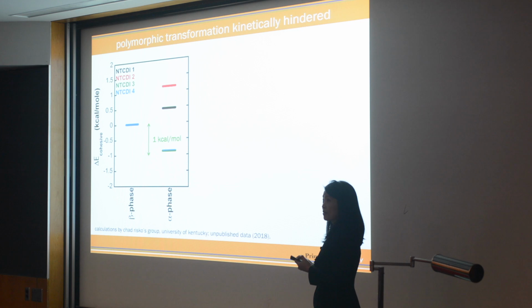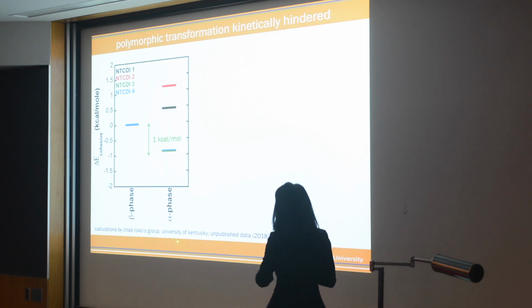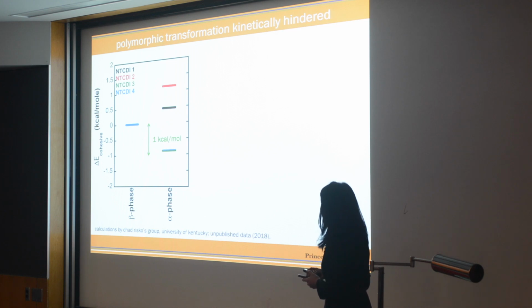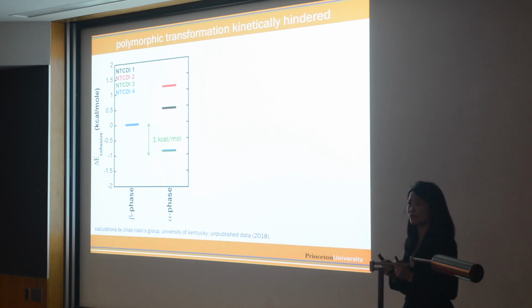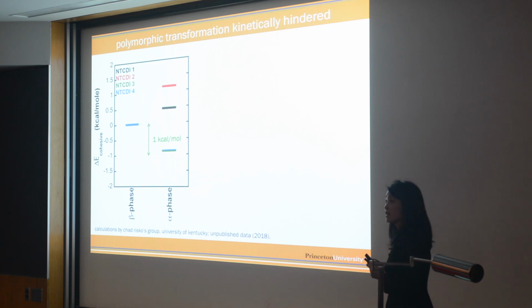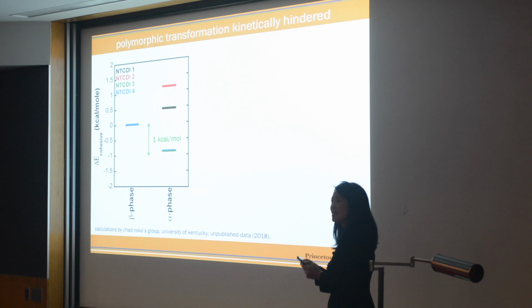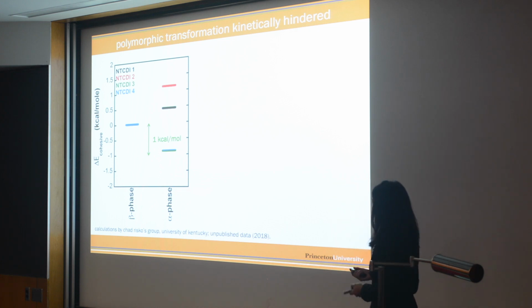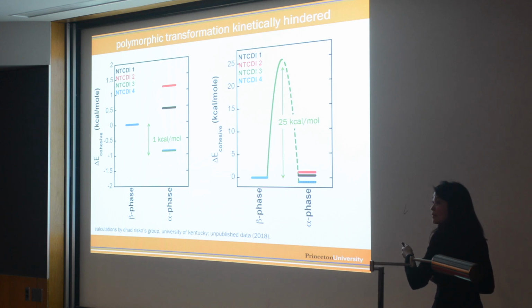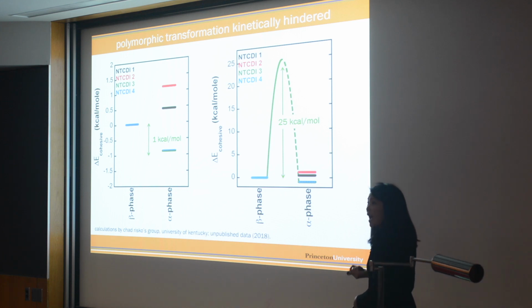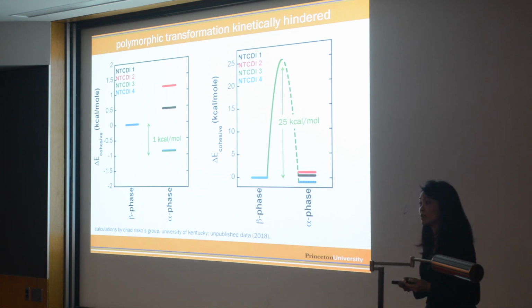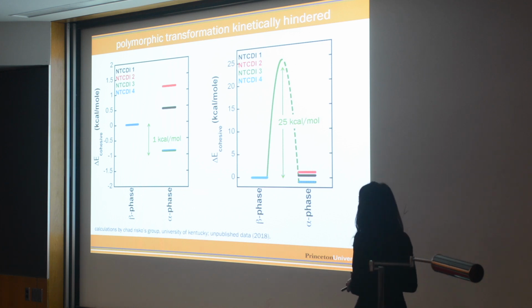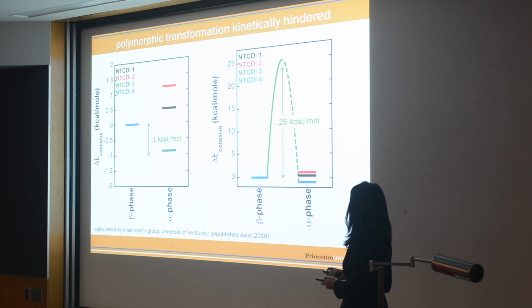Now, let's come back and talk about thermodynamics versus kinetics. Chad Risko at the University of Kentucky had done some calculations for us. This is looking at the enthalpic contributions of the energy, measuring the cohesive energy density. It turns out that the difference in cohesive energy density between the alpha and beta phases is very small, bringing us back to this idea that these aren't thermodynamically very different. What's different, though, is the kinetic barrier. Because we can do those kinetic measurements, we can back out an activation energy, and that activation energy is much, much bigger than the thermodynamic difference between these two polymorphs. So it appears that the constraint is on the kinetic end.